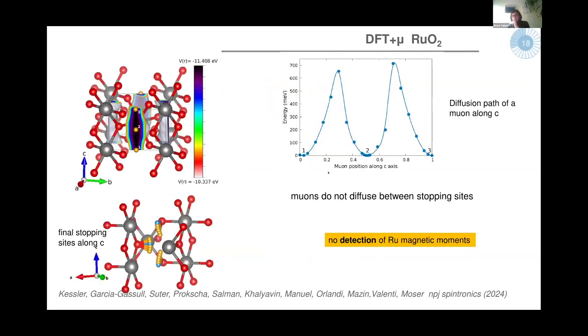Then Laura also calculated whether there could be some possible diffusion. Laura and Igor were doing these calculations to see whether the muons could possibly diffuse, because then again your signals could be influenced by diffusion. What I'm showing here are the 3 positions where the muon can sit. And this is the calculation of the energy, by considering the position of the muon along this line here. As you can see, there are very well defined wells in energy, which tells us that we are not going to expect effects of diffusion.